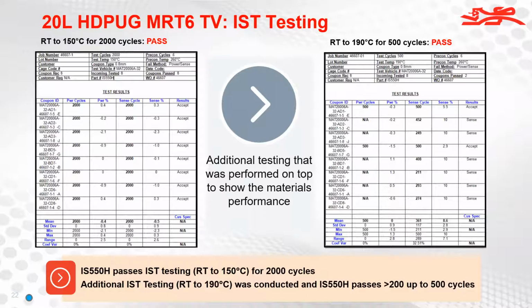And this answers the need of, if I'm turning my system on and off over and over again for thousands of cycles, what is this material going to do if I put it into my design? I think this addresses that particular need pretty well. It gives you a really good understanding of how this material performs. If you put FR4 in this same test program, it would more than likely fail, especially when you're going up to 190 C, which is well above most FR4 materials' TG.